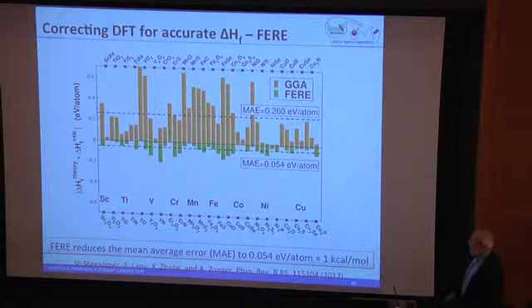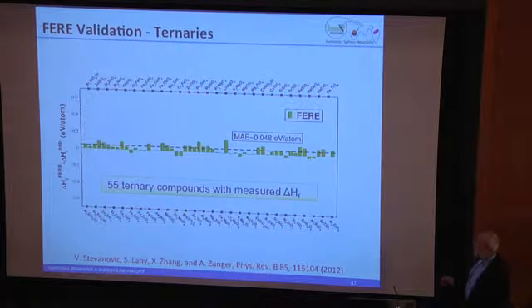But what it allows them to do is, even on ternary materials, it allows them now to calculate the heat of formation reasonably accurately because there's not this big dispersion from DFT anymore. And as far as I can tell, from what we can tell, it actually is correct. So whatever it is, usable, right?